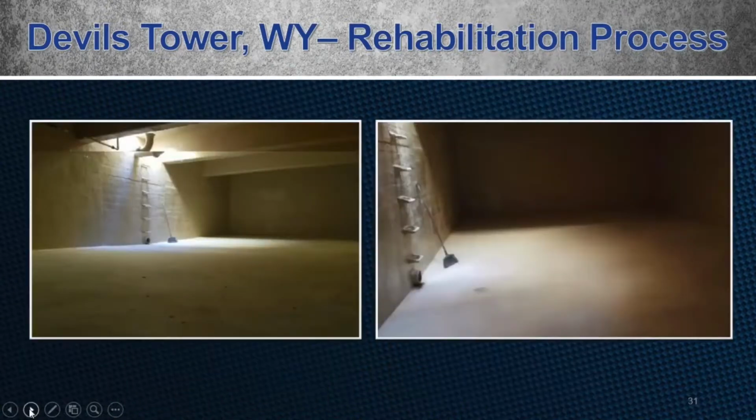The following morning, the Quadaflex 506 polyurethane was applied by heated plural component airless equipment at 100 mils dry film thickness over the entire surface. Approximately 4 hours after the application of the urethane lining, the entire surface was checked for pinholes and holidays by high voltage spark testing per ASTM D4787. Once those were all repaired, the tank was sanitized for potable water storage and placed back into service immediately. One of the big benefits of the system that was selected.